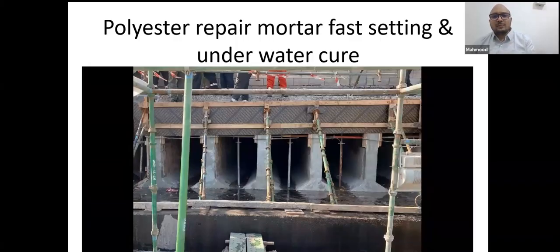They chipped it and made a formwork. I suggested a polyester repair mortar because it will set very fast. Within 2 hours, it will achieve higher strength than concrete, and also if the water comes, it can cure even underwater.